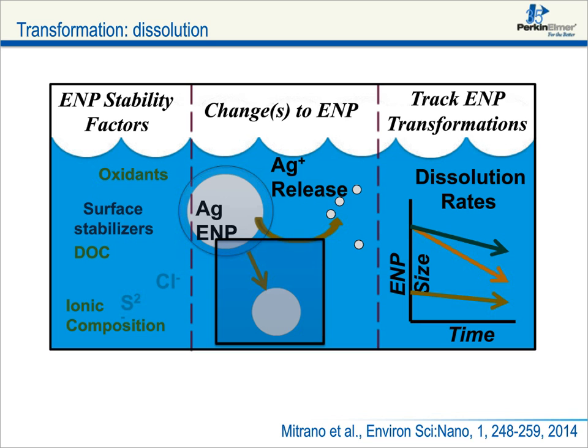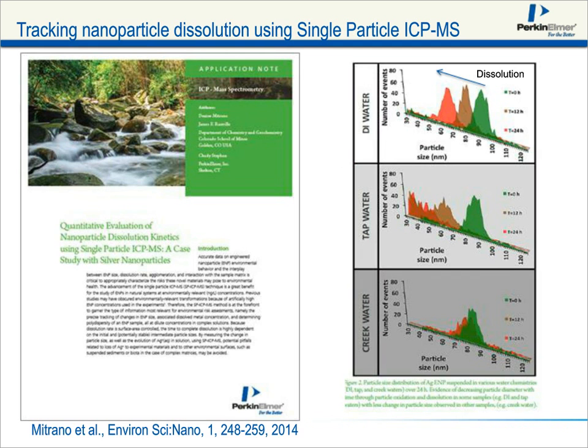We put together an application note a while ago, and from that application note we have the figures on the right, which simply show that in different media, DI water, tap water, local stream water, the rates of dissolution are varied. What's shown in the upper right is a series of distributions. These are still presented as particle size, where you can see our 90 nanometer particle at time 0 is shrinking in size. What's not really shown very well because we removed it is, as Kevin pointed out, the dissolved ion background is increasing.